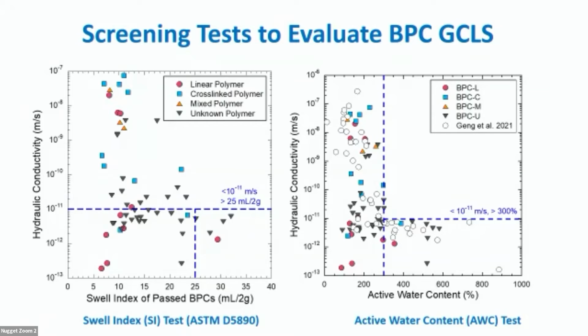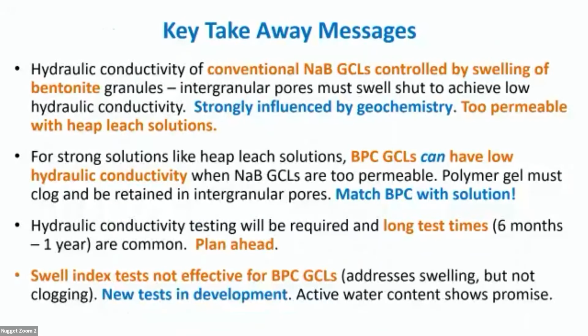Sometimes you'll see in the literature that people suggest using a swell index test to run a quick experiment to determine whether these materials will work, and just a caution, they won't, but we're working on some index tests that will. Just some key takeaway messages: the conventional GCL is strongly influenced by the geochemistry, and really they're too permeable for heap leach solutions. The BPC GCLs can work. We want to match the GCL with the solution.